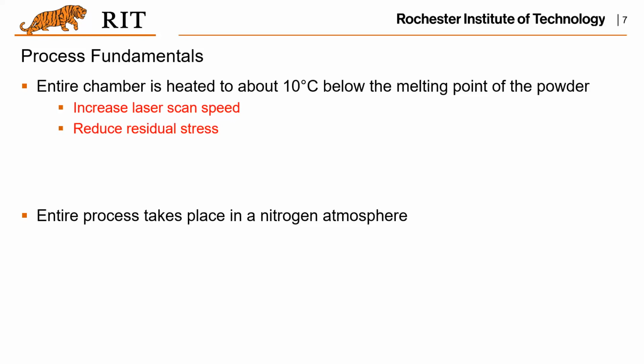Another benefit is from the material property perspective. Because the temperature difference is small, the built part will have less residual stress. So in order to reduce such residual stress, it is desired to heat up the whole part to a certain temperature, which is 10 degrees Celsius below the melting point.